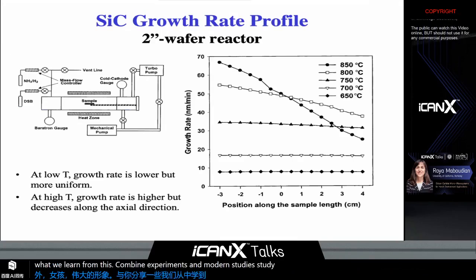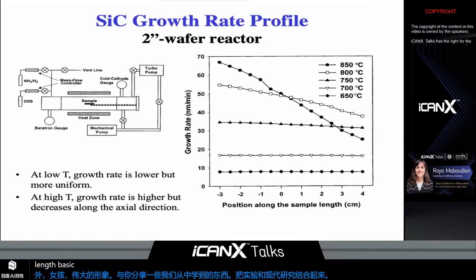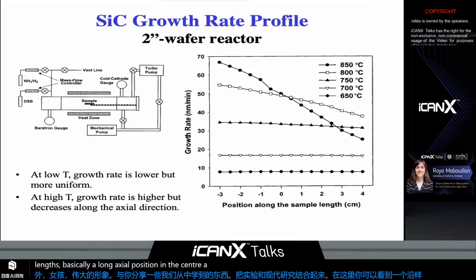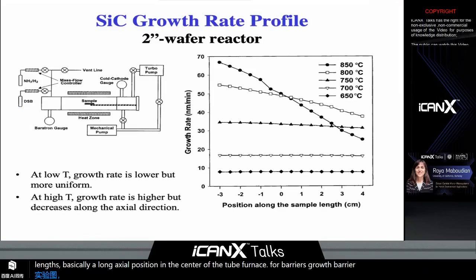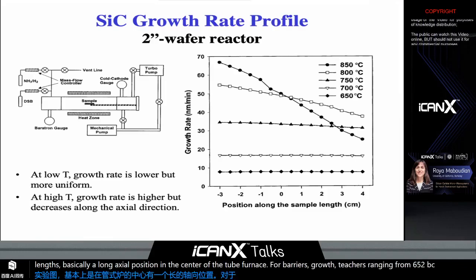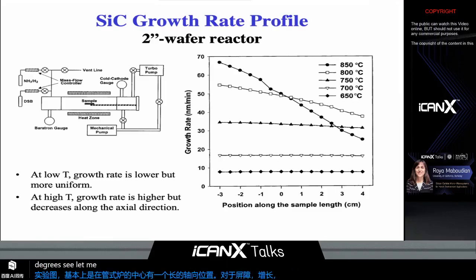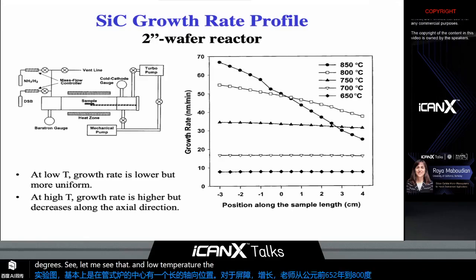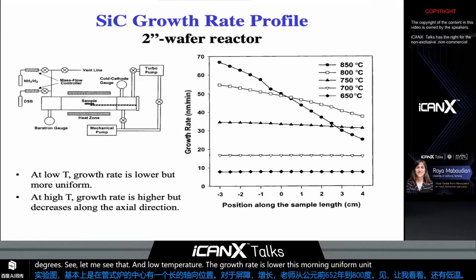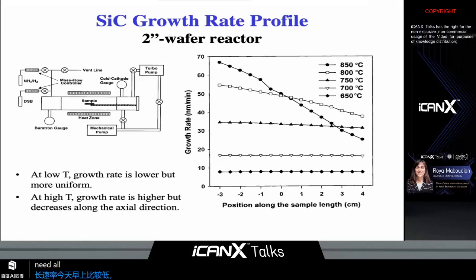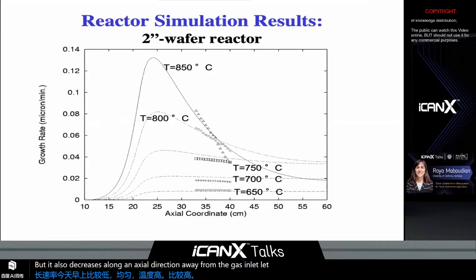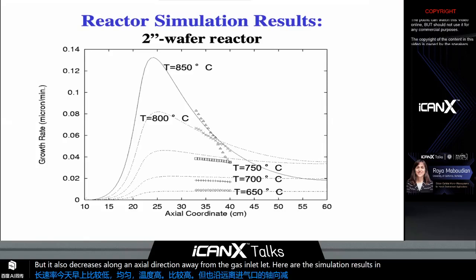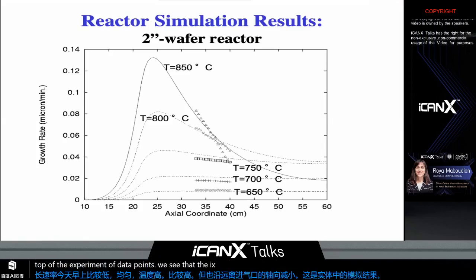Here you see a plot of experimental growth rates along sample length, basically along axial position in the center of the tube furnace for various growth temperatures, ranging from 650 degrees C to 850 degrees C. What we see is that at low temperature, the growth rate is lower, but is more uniform. At high temperature, it is higher, but it also decreases along the axial direction away from the gas inlet. Here, the simulation results in solid lines are plotted on top of the experimental data points. We see that the experimental trends are well reproduced by the model.